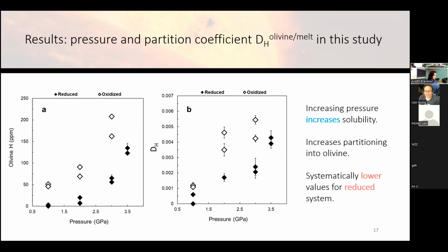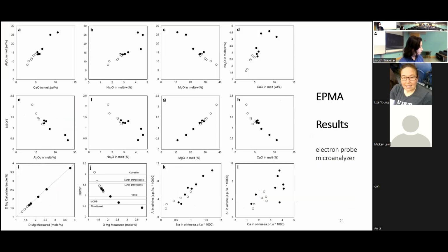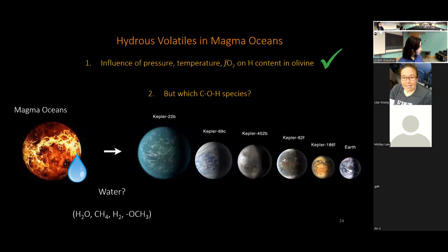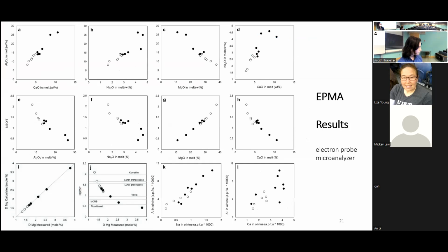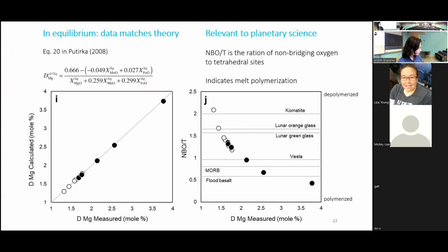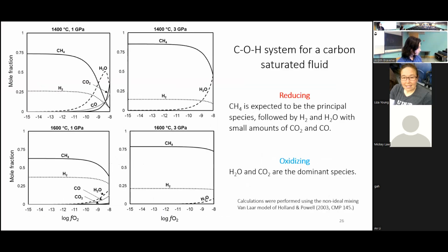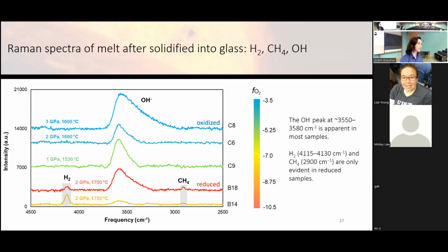And as for how it's incorporated, that gets a little bit difficult too, because these samples aren't appropriate for fingerprinting incorporation sites like you might be able to do in a larger crystal sample with spectroscopic studies. So it's kind of impossible to know. But I would say if it's H2, that's small enough to interstitially fit within the crystal structure.